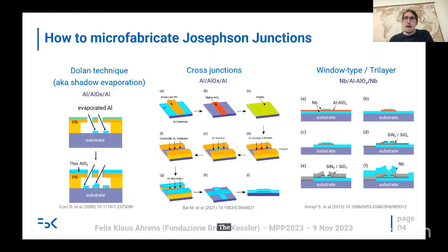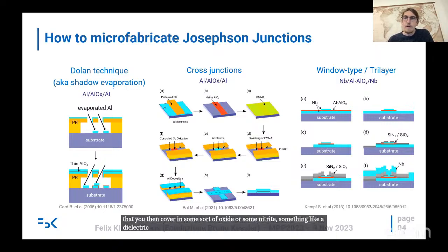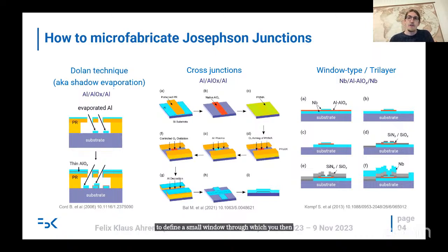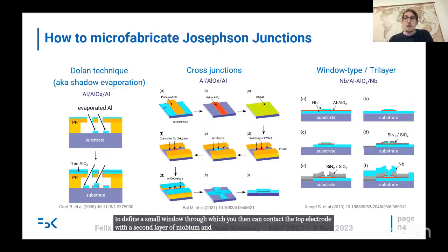The third process is the window type or tri-layer process, where you grow, for example, an aluminium oxide junction between two layers of niobium. So you deposit niobium, aluminium, you oxidize the aluminium and put niobium on top, which allows you to pattern a small junction that you then cover in some sort of oxide or some nitride, something like a dielectric, to define a small window through which you then can contact the top electrode with a second layer of niobium. And in that way, you have a Josephson junction between two layers, which gives you very much flexibility in terms of size and also geometries you can do. However, the disadvantage is that you have some sort of dielectric in between, which might introduce problems, for example, for qubits, because dielectrics typically tend to be lossy, and it's something we do not want for qubits.